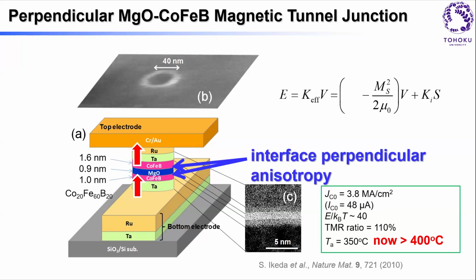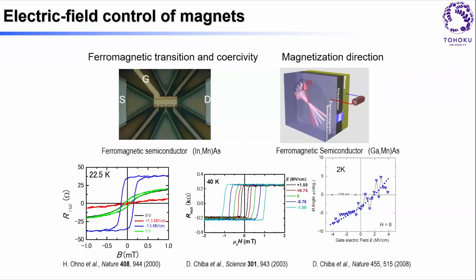We did this systematic investigation because we've been working on electric field control of magnets using indium manganese arsenide, gallium manganese arsenide, at low temperatures, and also at room temperature electric field control of iron, cobalt, and so on and so forth. But in order to see the effect, we have to make the layer extremely thin. And that's how we discovered this.